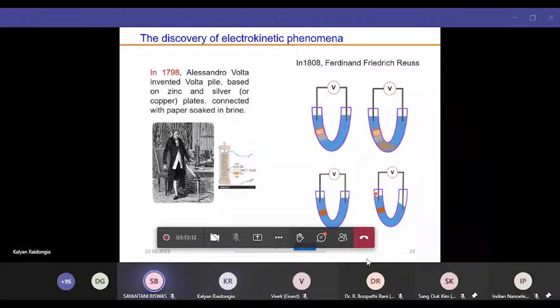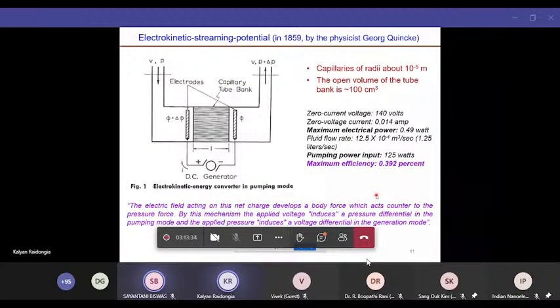So what we know from this is that if you apply voltage through a charge-selective filter, then ions can move to one side, which will generate a pressure difference, which is electroosmosis. That the water level is changing means the pressure on both sides is changing. Similarly, a reverse experiment was done by Georg Quincke in 1859. He assembled a large number of capillary channels. At that time, capillaries with a radius of around a few tens of microns were the best that could be made, because we are talking about very early times. He put a large number of capillary channels in a U-shaped device. Then he applied a pressure.